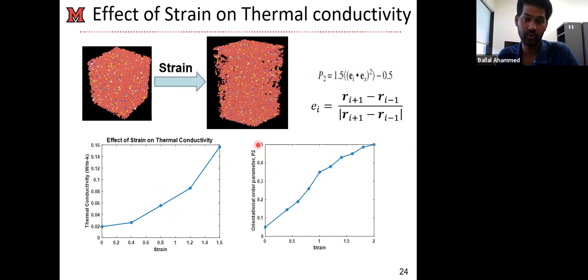We actually introduced a property, which is there in the literature. It's called the orientational order parameter. It is a measure of how straight your polymer chain is. So you calculate this parameter with the strain. We found that it's increasing with the strain. That means your polymer chain is getting straighter as you are straining the material. That is very expected. This orientational order parameter can have a value between 0 and 1. 0 means your polymer chain is very curled up, and 1 means your polymer chain is very straight. And it is, of course, averaged over all the polymer chains we have in this material. So it says that with the strain, the straightness is increasing, and this straightness is helping the material to have better thermal conductivity.